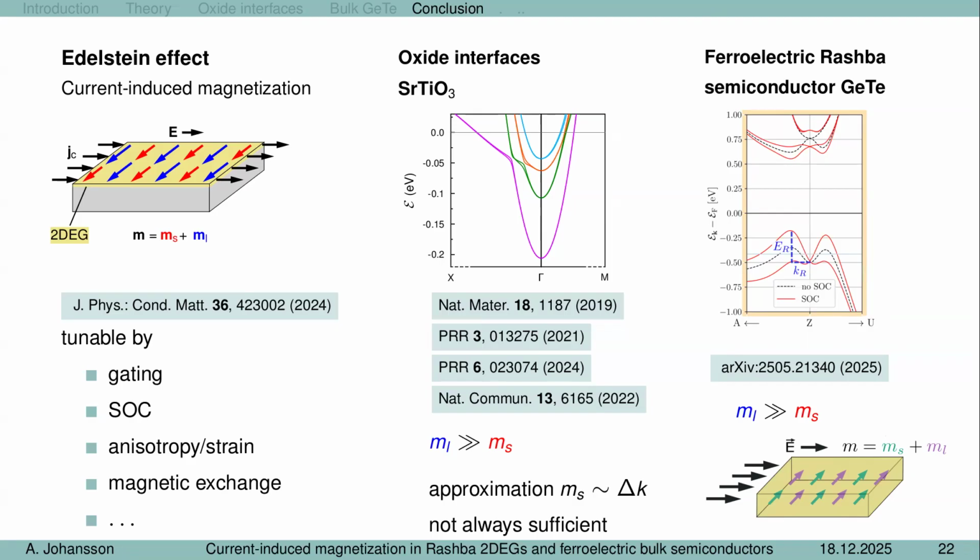But I think you're raising a point, because my impression is that for the magneto-optical properties of a system, if you measure MOKE, for example, you actually measure the orbital contribution. You never measure the spin. The spin is just a perturbation of the orbital. We've been using MOKE to measure magnetism, but that's because of the spin-orbit coupling. If you remove spin-orbit coupling, you cannot get the magnetism through MOKE. So perhaps there is something in this direction, but I agree with you. We have to work more.